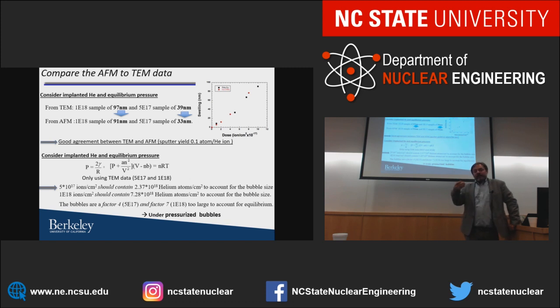Now, if you already created a seed for a bubble and some helium, now the vacancies are going to join that. In the 1 times 10 to the 18 ions per square centimeter, that's a dose of 40 dpa, which is, of course, quite high. And so it's not just the bubbles themselves, but it's also the vacancies joining those bubbles at these incredibly high dpa rates, 40 dpa within an hour, is quite significant. And so these bubbles tend to be not in equilibrium pressure.